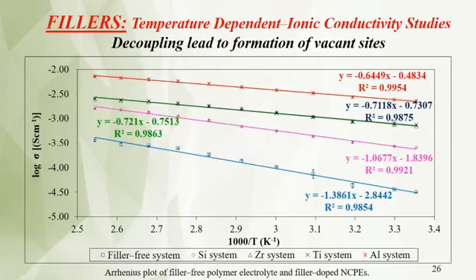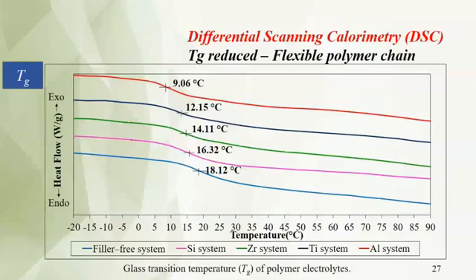Okay, now I'm going to share with you all how the nanomaterials work on polymers. So from this result, we can see the incorporation of the nanoparticles can increase the ionic conductivity, and also we can observe with the increase in temperature, the conductivity increases. This temperature-dependent ionic conductivity is crucial in studying the mechanism of the electrochemical devices. And we also can observe here the nanoparticles can decrease the glass transition temperature of the system, which shows that the flexibility of the polymer membrane is improved by incorporating nanoparticles.